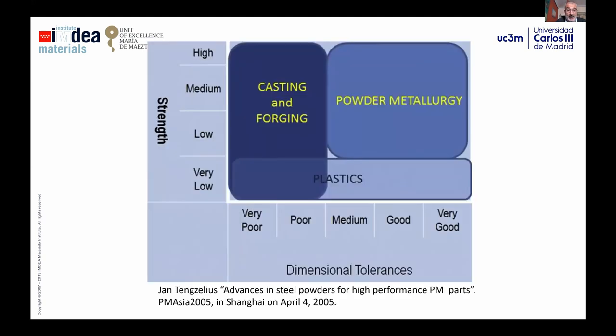So conventional powder metallurgy used to be represented in maps like this, in which we represent the strength against the dimensional tolerance, because dimensional tolerance is one of the advantages of conventional powder metallurgy. But the level of properties between the lower level and the high level is highly linked to the way in which we obtain the powder metallurgy part. If we go to press and sintering, we will have the materials on this side of the map, in which we have a high level of dimensional tolerance but a low level of strength. If we improve the processing methods and go to a lower level of porosity, we move in this direction, and we can even reach a high level of strength with medium to poor dimensional tolerances, but these materials can compete with any other material from alternative processing techniques.